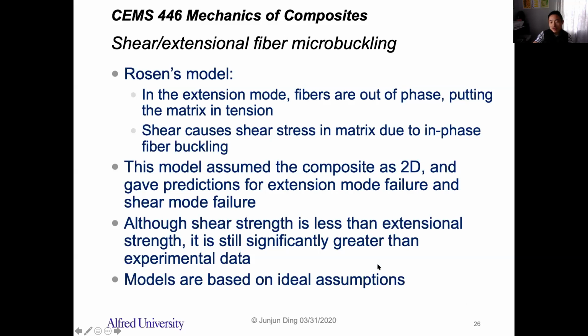Although the shear strength is less than extensional strength, it's still significantly greater than the experimental data. It's based on the ideal assumptions. But it's a great way to predict whether you will have the shear fiber microbuckling or extensional fiber microbuckling.